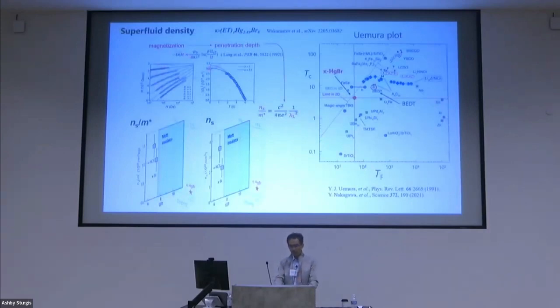Superfluid density is extracted from the penetration depth measurements, and then this is the half-filled plane, and this is the doping axis here. The half-filled band material, a non-superconductor, shows the expected value of n over m star, while this material should show zero. So there is a very large missing superfluid density, in other words, a reduced superfluid density. So roughly speaking, of the total carriers, only about 25% contribute to superconductivity.